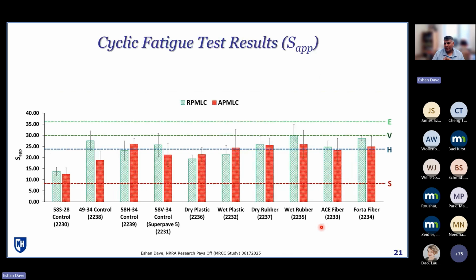Cyclic fatigue. So as I said, we'll just use one parameter here, the SAP parameter, which Federal Highways is proposing and recommending. There's actually an info brief from Federal Highways that also gives the limits. And it uses the same kind of criteria as the MSCR binder grading, where you have your standard, heavy, very heavy, and extreme traffic levels in terms of millions of ESALs that this roadway might be experiencing. Since it's tied to fatigue cracking, it makes sense to have the limits tied to the traffic levels.